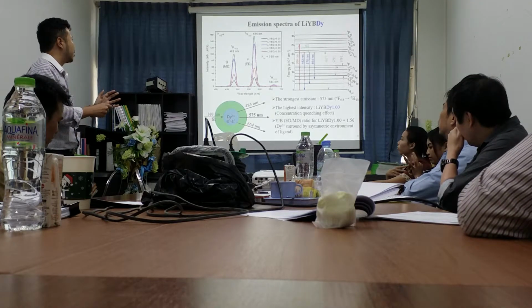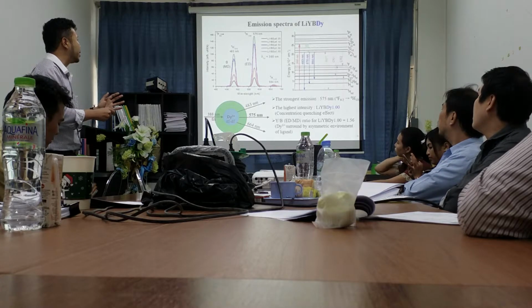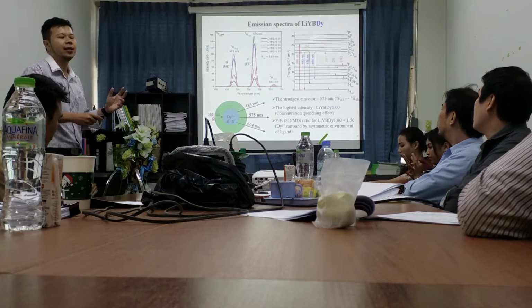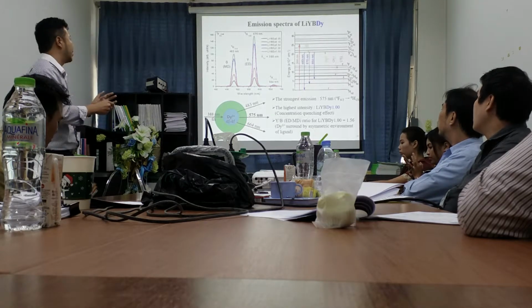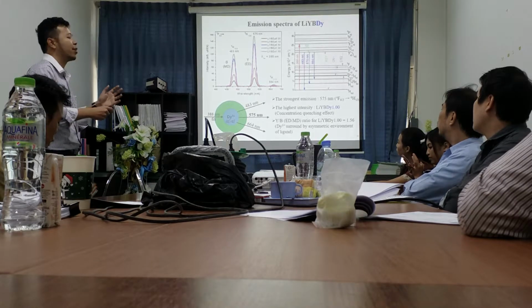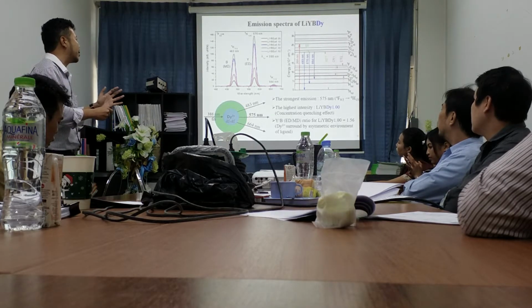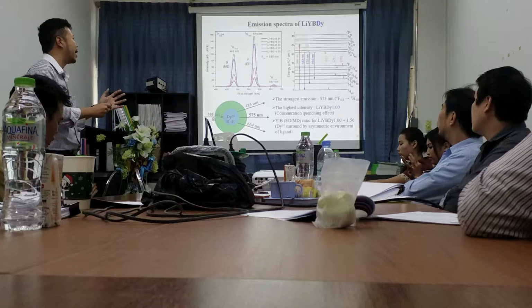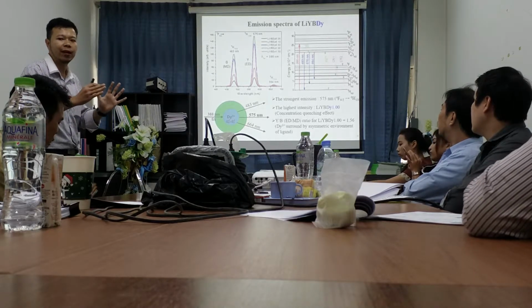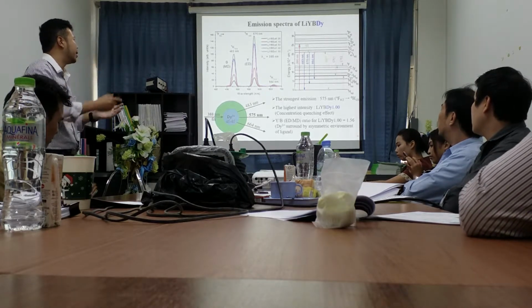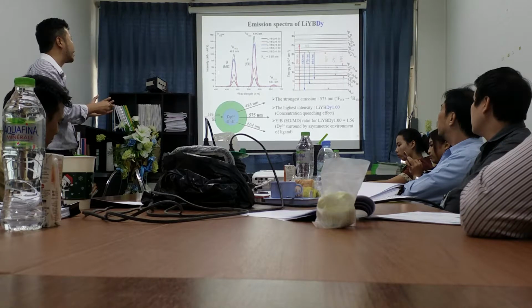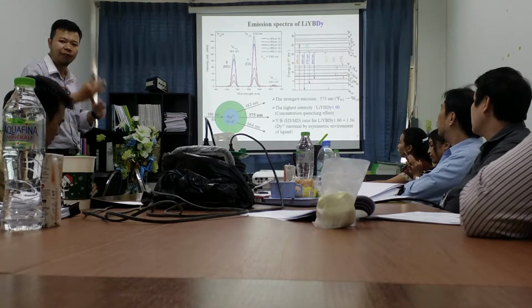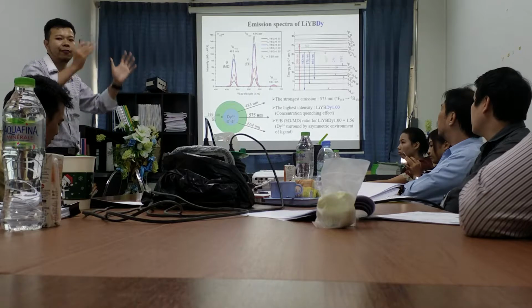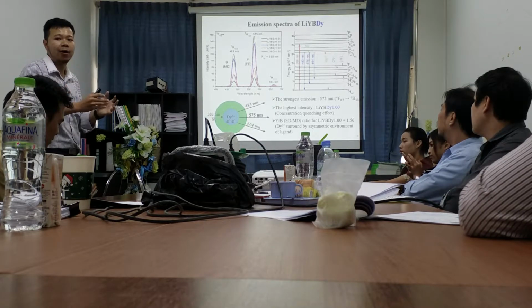Moreover, the strongest one is the peak from the electric dipole transition, and the other one is the magnetic dipole transition. The electric dipole transition is supported and enhanced by the asymmetric environment surrounding the dysprosium ion. If EDP is higher than MDP, this is a confirmation of the asymmetric environment surrounding the lanthanide ion in the glass.